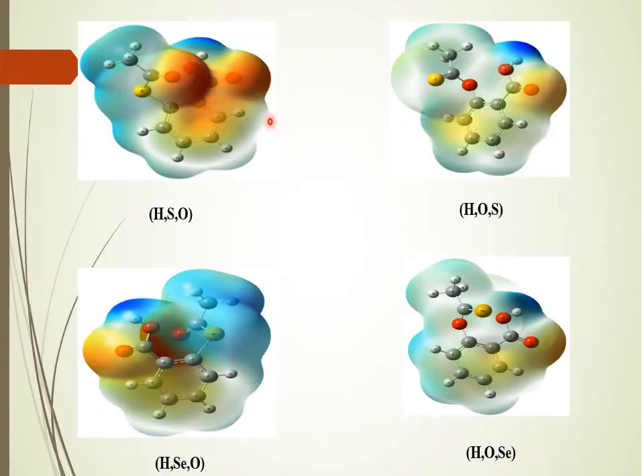Sulfur in the X2 position strengthens the electronegativity around the oxygen atom. The benzene ring increases the possibility of electrophilic interaction and creates a blue region. But on the other hand, sulfur in the X3 position leads to weakness of electronegativity, and the red color greatly disappears except around the oxygen atom of the carboxylic group. That increases the possibility to undergo a nucleophilic interaction. Selenium in position 2 or 3 follows the same pattern as sulfur.